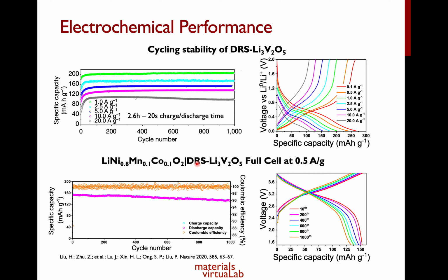They also constructed a full cell using an NMC cathode together with this disordered rock salt Li3V2O5 anode. And again, they can show extremely stable cycling up to more than 1,000 cycles. So in short, the performance of this disordered rock salt anode is actually very, very good. The rate capability is very good.